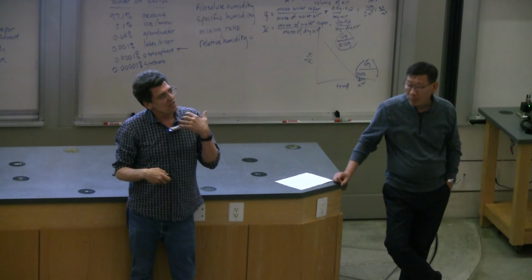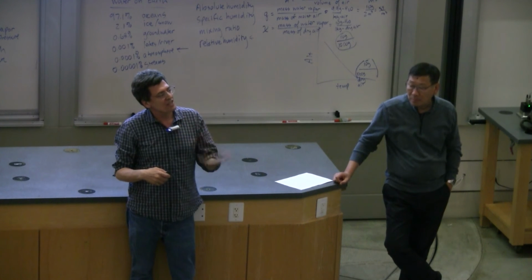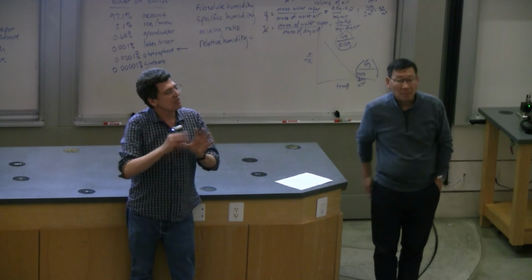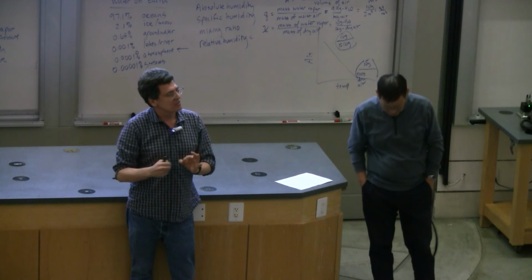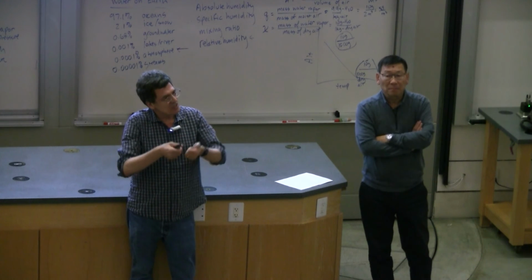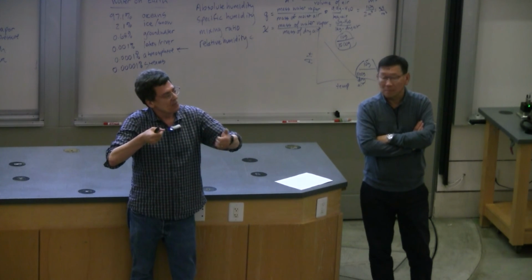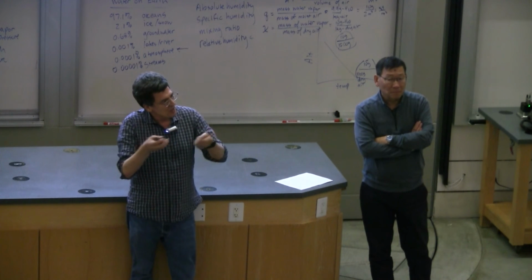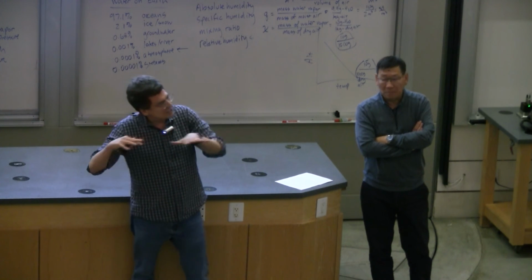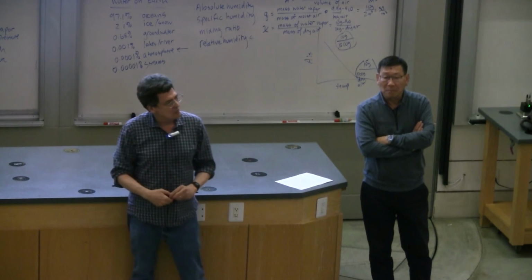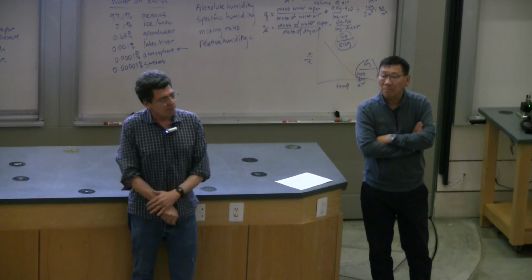But the one phase that was the most fragile was the n = 1/2, so the stripe phase. The other phases were much more robust. The stripe phase was very fragile. It only occurred over a very small range of parameters, and it was very sensitive to strain. And we could see the effect of strain by looking at the Moiré pattern. So the strain is going to affect that stripy pattern. That is really the most sensitive, fragile one. But the other ones were pretty robust.